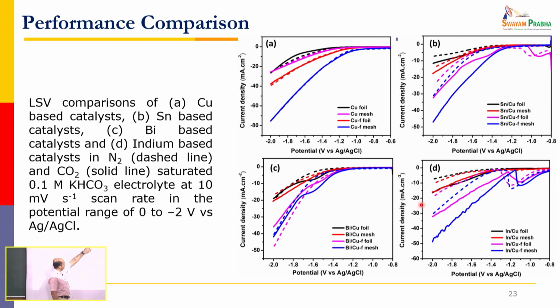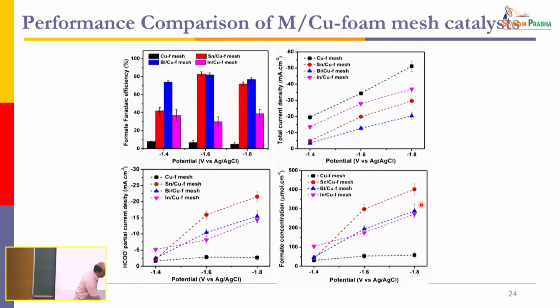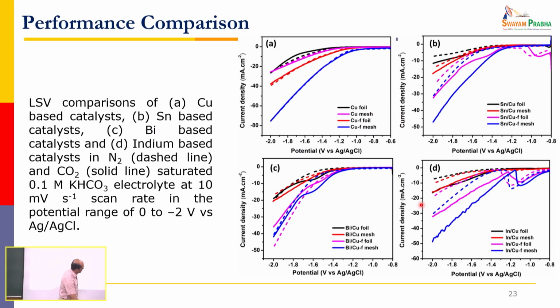So you run this experiment to find out. Here you can see the blue one is a better catalyst compared to the other two. If you look at it, you can get current density as high as 80 milliamp per centimeter square. You can get 80 milliamp for a copper foam which is developed on a mesh. So we have done this for different catalysts to find out which one is best. Higher is your current density, better is your catalyst. Usually it is a screening technique. When you have 10 materials, you can do cyclic voltammetry to figure out which is the best catalyst. Once we screen them, then we apply this potential. So here we have different potentials.